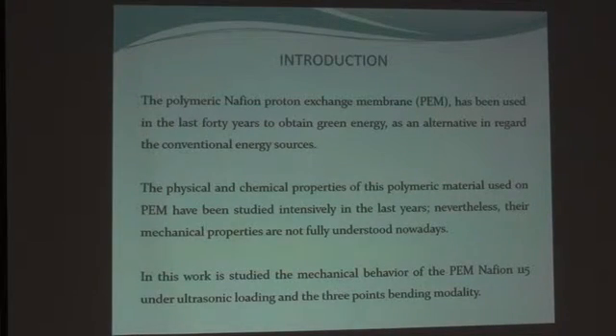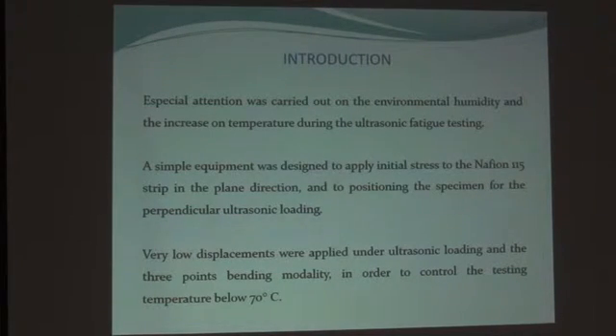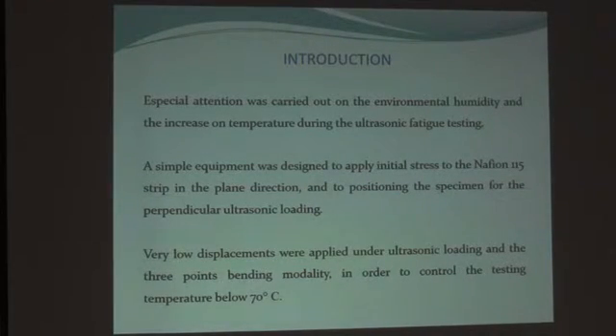In this work, the mechanical behavior of the proton exchange membrane Nafion 115 is studied under ultrasonic loading and 3-point bending modality. Special attention was paid to the environmental humidity and the increase of temperature during ultrasonic fatigue testing. A special equipment was designed to apply initial stress on the Nafion strip in the plane direction and to position the specimen for the perpendicular ultrasonic loading. Very low displacements were applied in the ultrasonic loading and 3-point bending modality in order to keep the testing temperature below 70 degrees Celsius. The glass transition temperature of this polymeric material is 110 degrees.